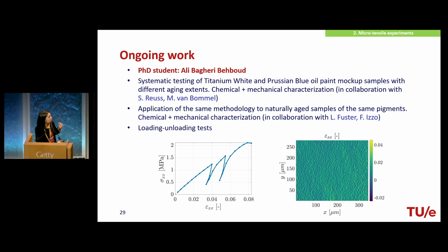What we want to see is that, although here we do not go to zero, and this is just a preliminary analysis, there is the appearance of some irreversible deformation, which opens new questions. Is this really irreversible deformation, or is this a deformation that will be recovered? So is it actually a viscous deformation, a viscoelastic deformation? There are several things that we can assess and learn from these tests.